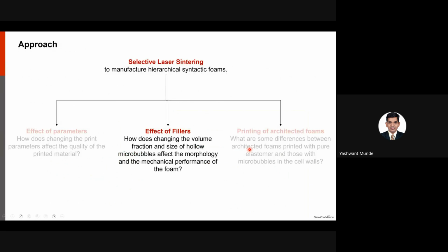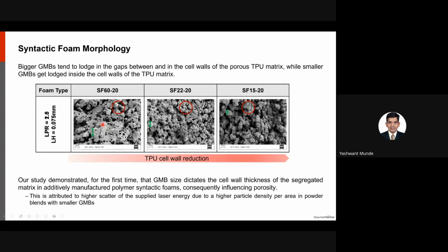So then we added fillers. We wanted to see how that changes the internal architecture and structure of these foam composites. Here are images. I'm showing only the 20% fraction as an example. This is for the bigger GMBs with mean diameter of 60, 22 smaller, and 15 the smallest particle size. We see that the bigger GMBs tend to get lodged between and within the TPU, sort of creating a bridge between these segregated TPU matrix regions, while the smaller particles were completely embedded within the cell walls, as you can see in these two cases, especially in this one.